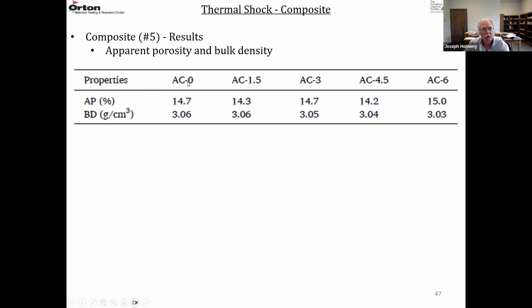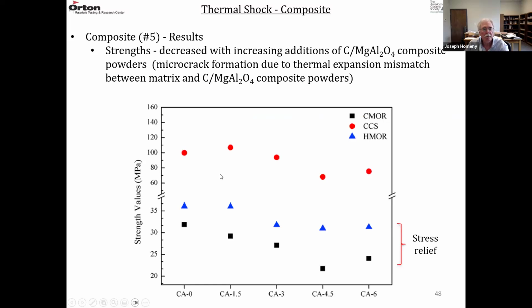So going from AC0 to AC6, the apparent porosities are all between basically 14 and 15. The bulk densities in grams per cubic centimeter are all just a little higher than 3. So there was no real difference in porosity and density on these materials.